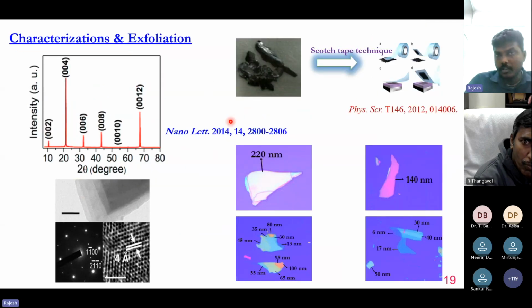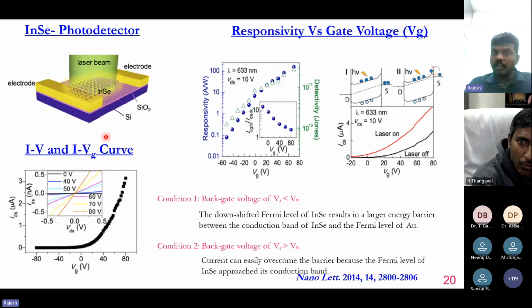This is our grown indium selenide, and with the help of Scotch tape exfoliation, we fabricated various thicknesses of indium selenide, and we demonstrated the single crystalline nature with the help of XRD and SAD pattern, which confirm the single crystalline nature of our grown material. Then, with the help of the shadow mask technique, we fabricated a phototransistor device. Then we shine light on our material.